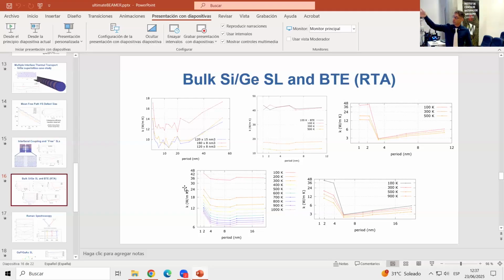It's because here you plug the interfacial effect in by hand, taking it from a phenomenological model. I'm not sure, to be honest, if they actually put a temperature dependent scattering rate for the interfaces when they implemented the code. Yeah, because I would really guess that you would observe a shift in the position of the minima. This is physics. This to me is physical intuition.